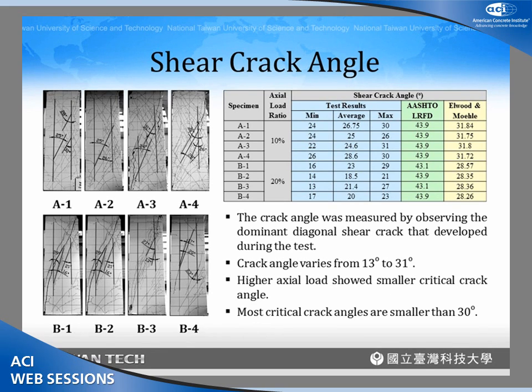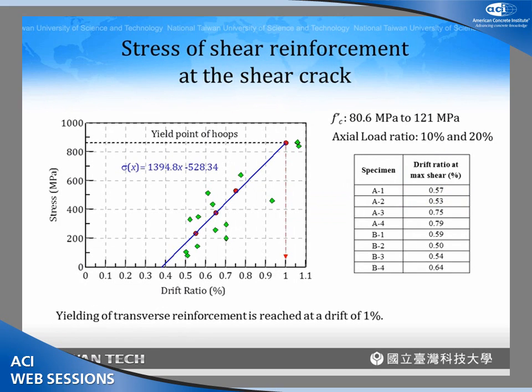And this slide shows you how we observe the shear cracking angle from the eight specimens. And we found that the shear crack angle is about 25 degrees for 10% axial load, and it reduced to about 20 degrees for 20% axial load.